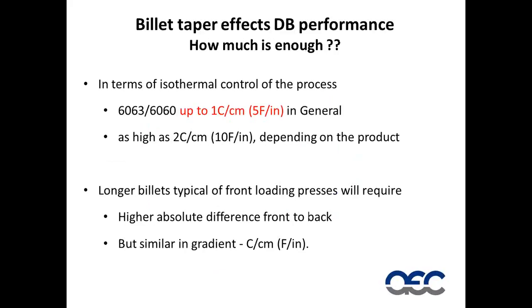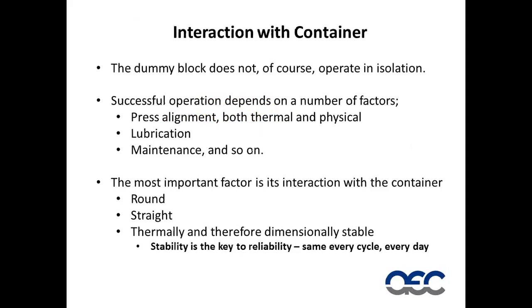Today, with 6000 series billets, what we're seeing in general is about 5 degrees Fahrenheit per inch taper is required to be a super extruder. I'll go back to my old word. There are some extruders globally that are using as much as 10 degrees Fahrenheit per inch. I think this is pretty aggressive, but Richard? Oh, it's aggressive. But 5 degrees Fahrenheit per inch would be probably acceptable. About 100 degrees centigrade per meter. Okay. So yes. Very good. Thank you. The dummy block also interacts with the container.